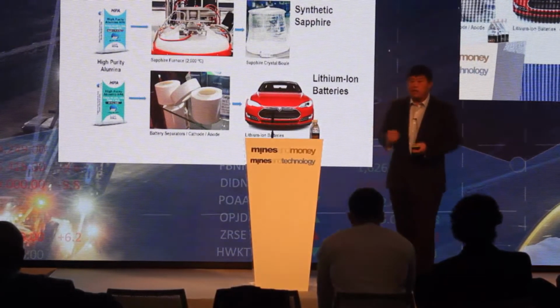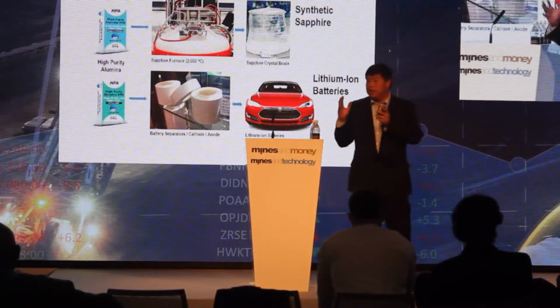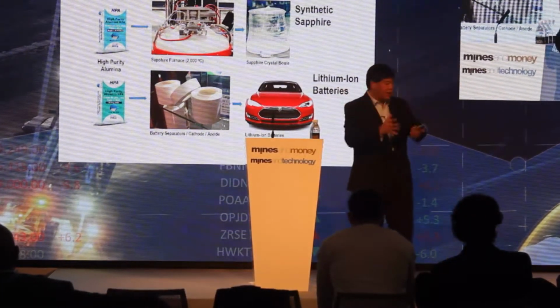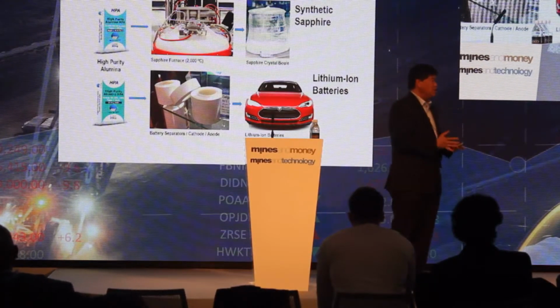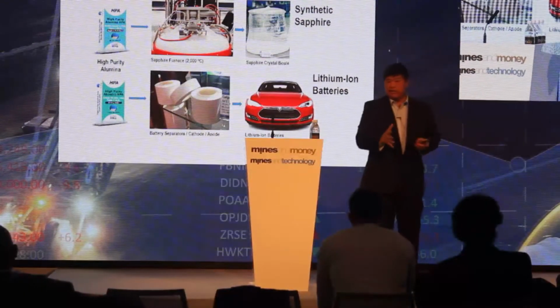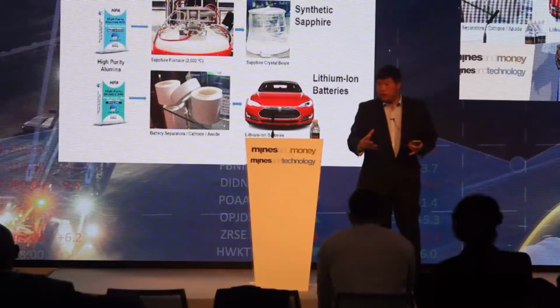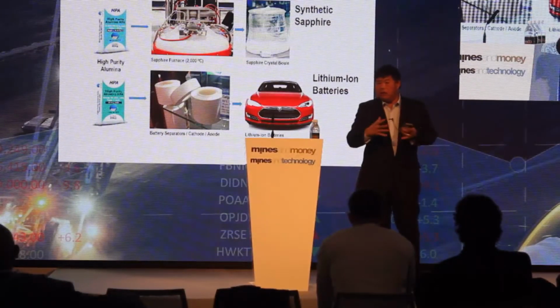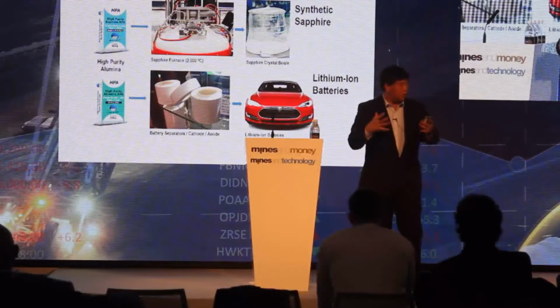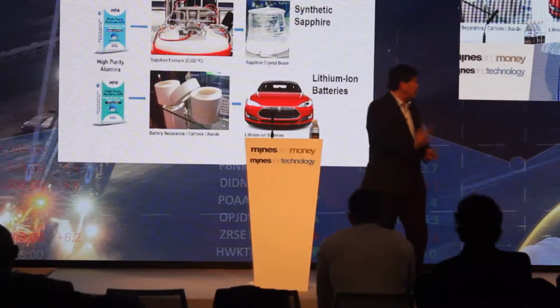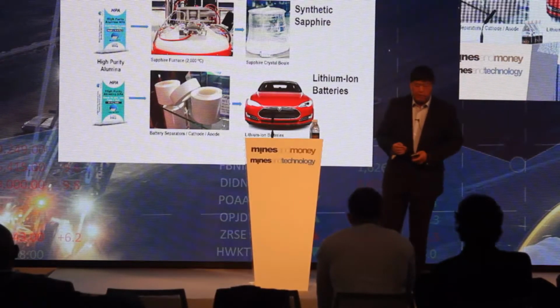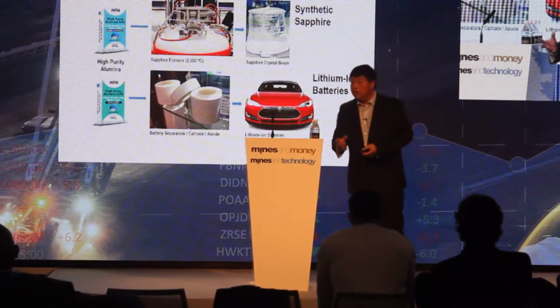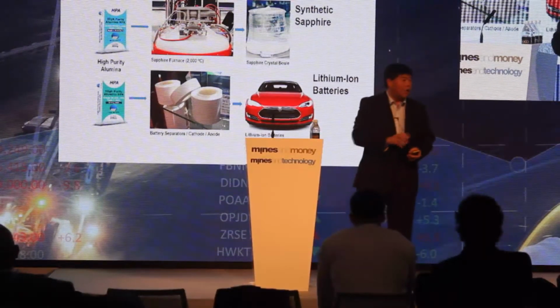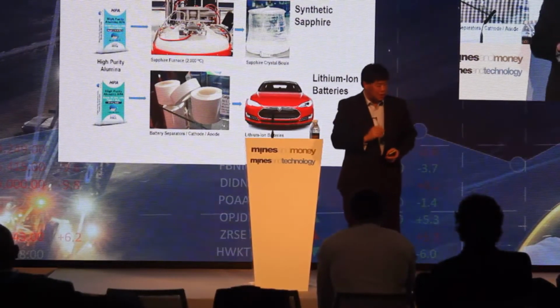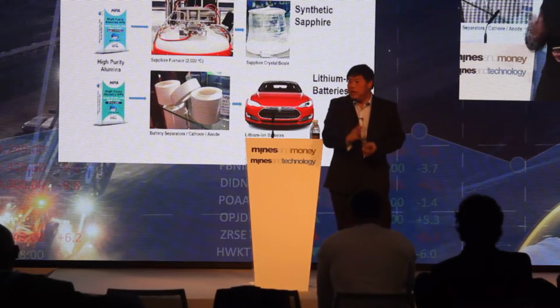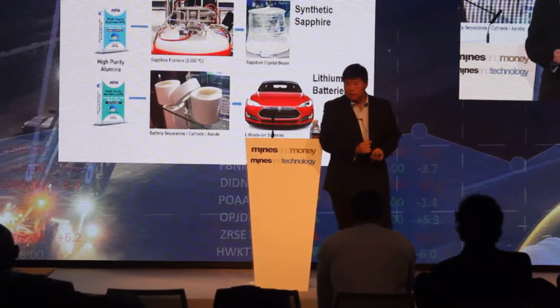The way they make synthetic sapphire today is basically they buy high purity alumina, they stick it in the furnace, heat it up to 2,000 degrees. It's nearly as hot as the sun. Alumina melts, and they cool it over 21 days and grow a single crystal of sapphire. That's what it looks like, a big ice block. Nearly as hard as diamond, and the only way they can core it out is using diamond cores, and from that they slice it up to make sapphire wafers.